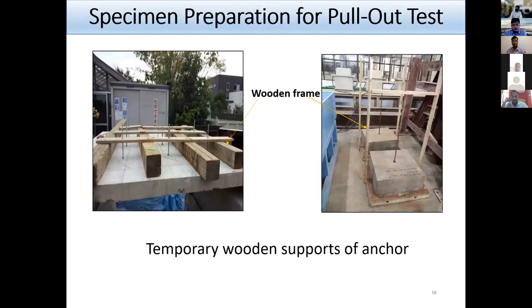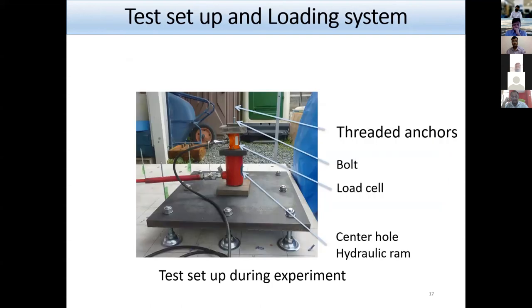After making holes in the specimen and filling them with epoxy and inserting the anchor, it was kept untouched for 24 hours using temporary wooden supports. This is the test setup and loading system used. A center-hole hydraulic ram was used to apply the load in the specified direction.